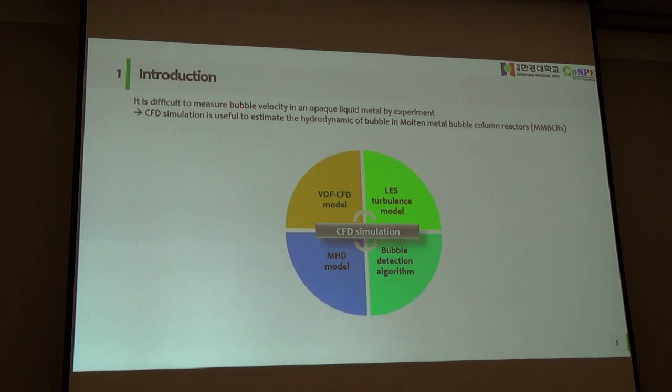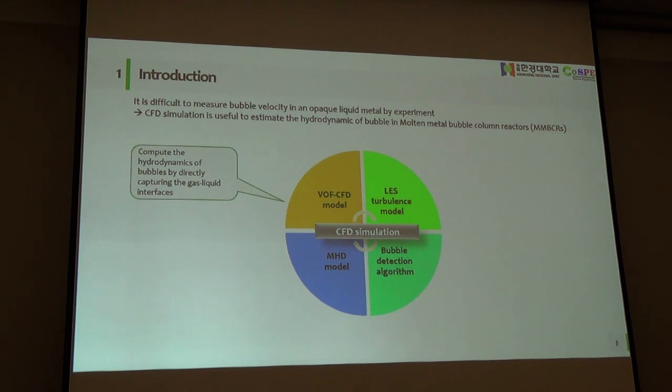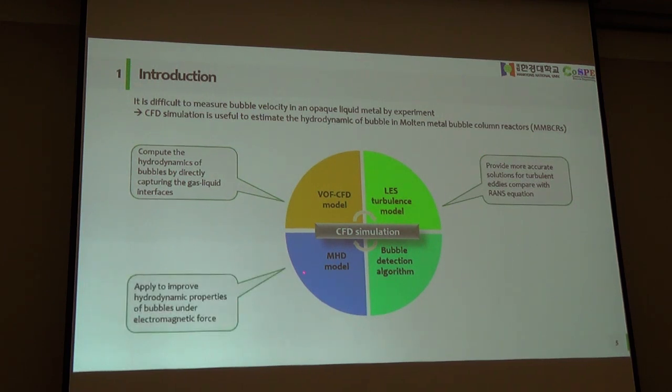It is difficult to measure the hydrodynamics of a bubble because in the experiment, the liquid is opaque. So with the CFD simulation, it's useful to estimate the hydrodynamics of a bubble in molten-metal bubble column reactor. In the CFD simulation, I use the VOF CFD model to compute the hydrodynamics of a bubble directly capturing the gas-liquid interface. I also use the LES turbulent model to provide more accurate solutions for turbulent eddies compared with the RANS equation.